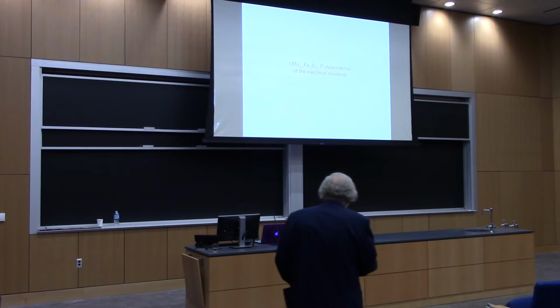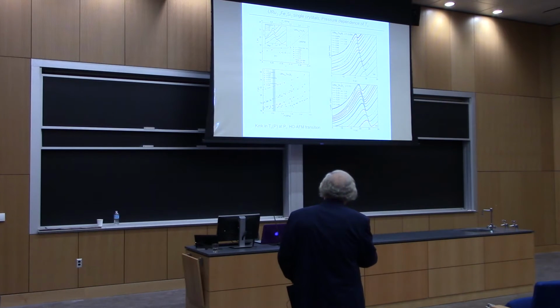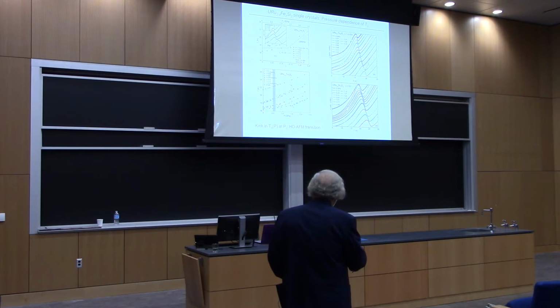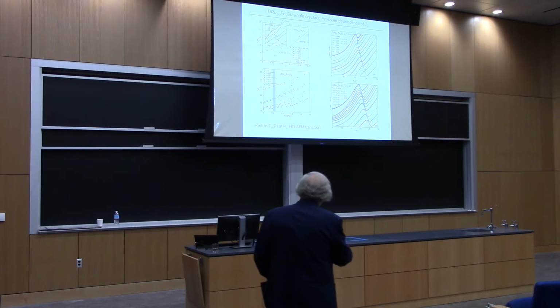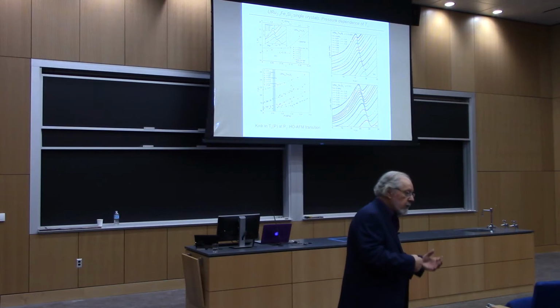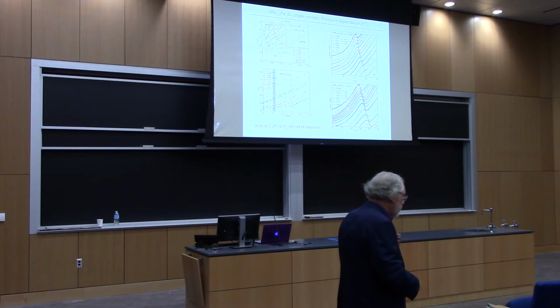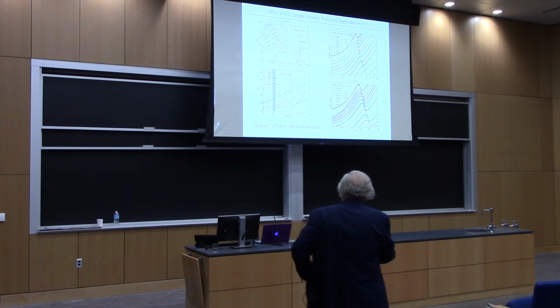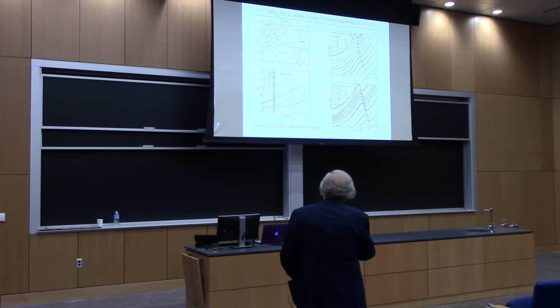Okay, we've done a lot of pressure-dependent work. I mentioned some of this a moment ago. And so here are the curves of the resistivity that you find under pressure. We've been interested in studying the kink in the phase boundary, where you go from the hidden order phase to the antiferromagnetic phase. This is for x equals 0, no iron. As you substitute iron, then iron is going to give rise to its own chemical pressure. So you'd expect this transition to occur at lower pressures, and indeed it does.